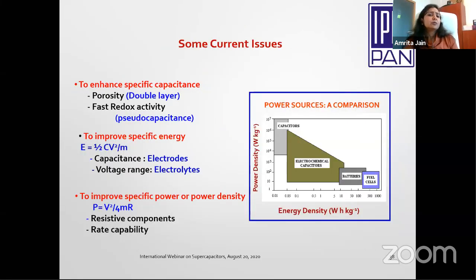Some current issues. For example, if we wanted to increase the specific capacitance, what can be done? One, to increase the porosity in case of double layer. And in case of pseudo-capacitance, increase the redox activity. Fast switching on, fast reactions. If you have fast reactions, then you have higher capacitance. If you have good porosity, you have good capacitance.